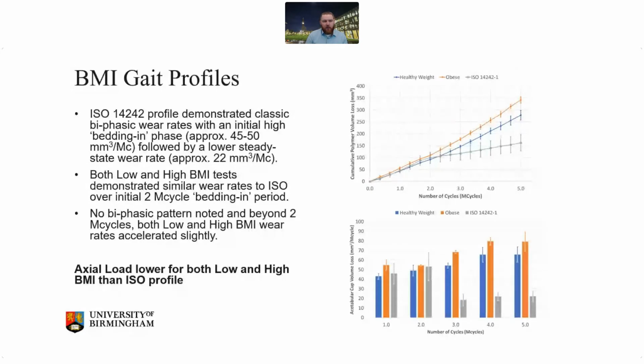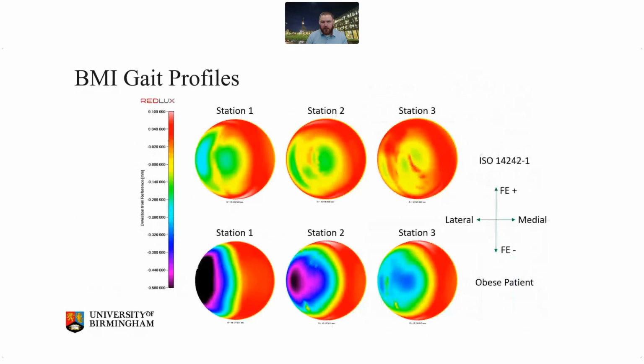Moving slightly away from wear rate, when we map the surface damage or the wear patch across the surface, what we see is a change into a more lateral wear patch. Because we introduced a medial-lateral force to match the kinematics, that resulted in more of a superolateral wear pattern, which has been noted clinically compared to the ISO profile.